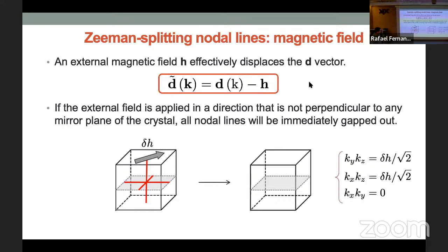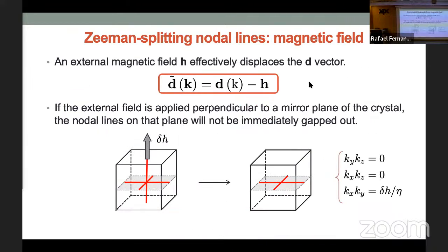So for example, here, I apply 45 degrees in the plane, and if you try to find where d tilde is 0, you can quickly convince yourself there's no solution to these three equations. But if I apply the magnetic field along a direction that is perpendicular to one of the mirror planes, so in other words, I'm keeping a mirror as a symmetry, then the nodal lines on that mirror cannot be immediately gapped. So it means that I have a much more stable altermagnetism here. For example, if I apply the field along the z-axis, I can still solve these equations by having kz equals 0.